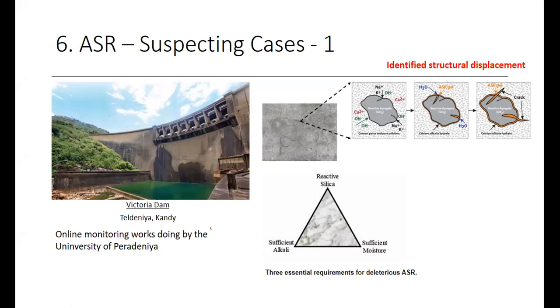Some researchers identified that elevated temperature or high temperature during the mass pouring also acts as a catalyst for this ASR reaction. So those are the three essential requirements for ASR formation. They should have reactive silica in the aggregates, sufficient moisture ingress to fulfill the required reaction media, and a sufficient amount of alkali.